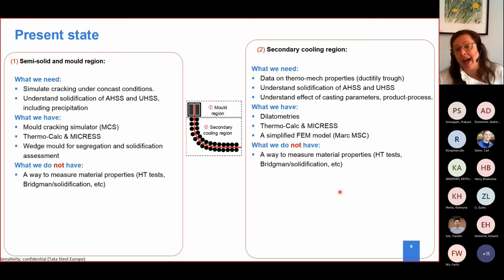What we have internally in Tata Steel, well, we have something I will show you later, called the Mould Cracking Simulator. We have a thermodynamic software, Thermo-Calc, and we have MICRESS, which is a microstructure phase field simulation software. We also have a wedge mold, which is a static ingot casting, and we are at the moment using it for analyzing segregation and the solidification itself.